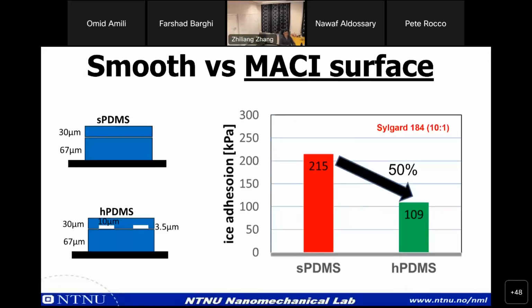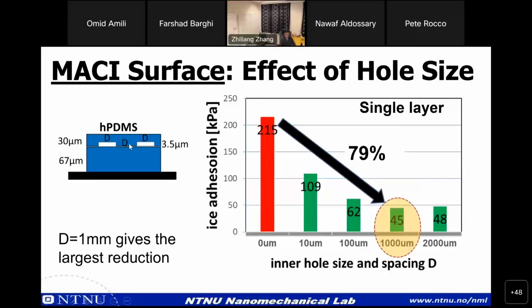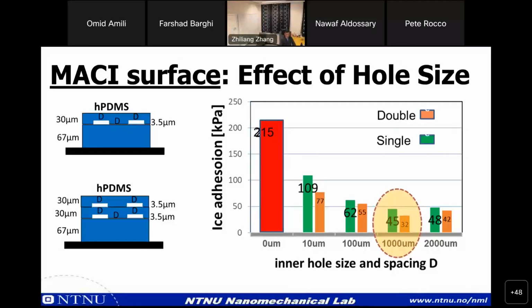So if you do something with the subsurface structure, we got immediately 50% reduction in the ice adhesion. So this is a very, very simple structure we have done. We can change the spacing and the width D from 10 micrometer to 100 to 1 millimeter. It seems at 1 millimeter we can get 80% reduction of the ice adhesion. We can have a double layer. If we use double layer, we get additionally 1/3 of reduction compared with the single layer.